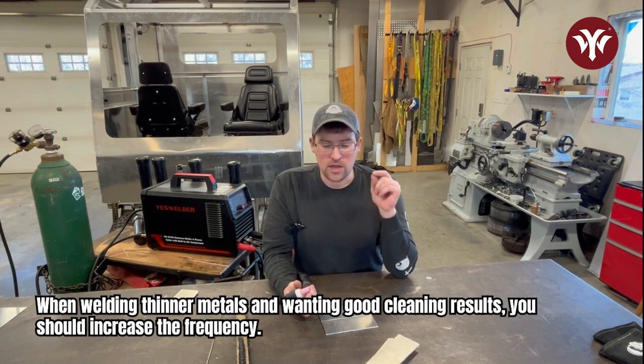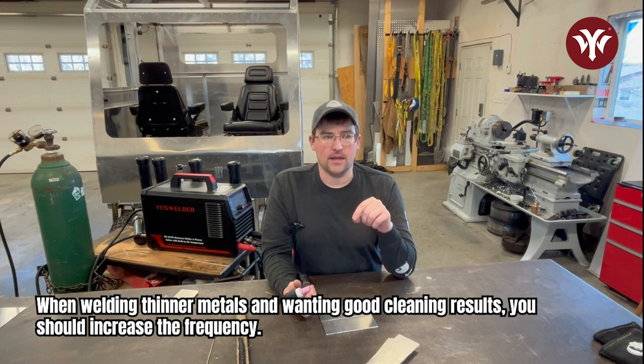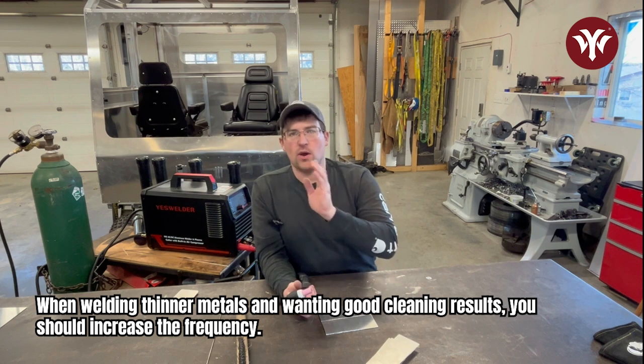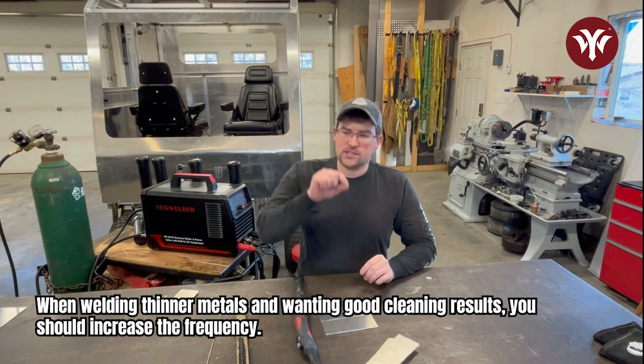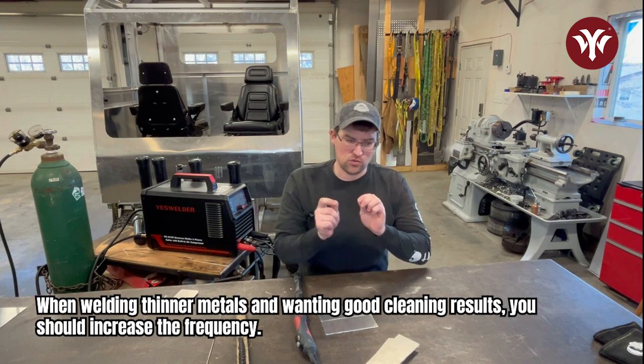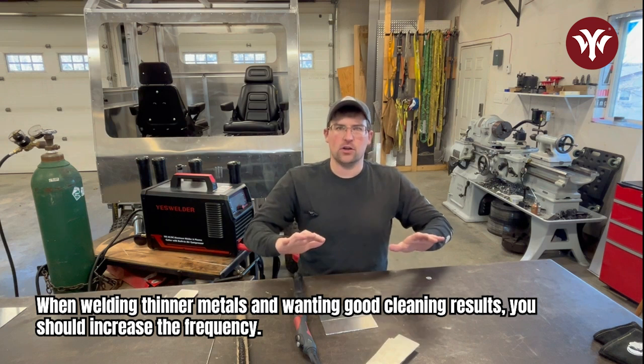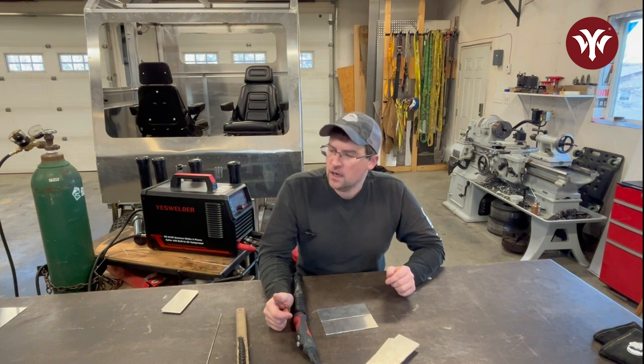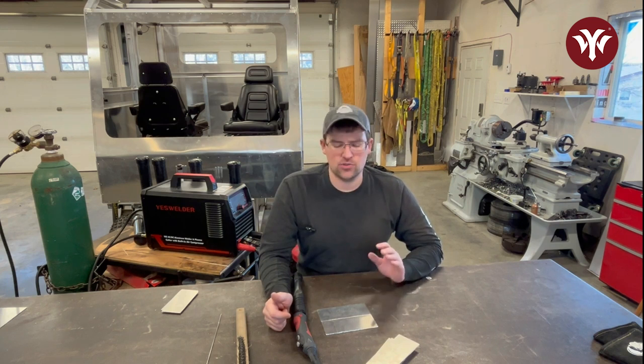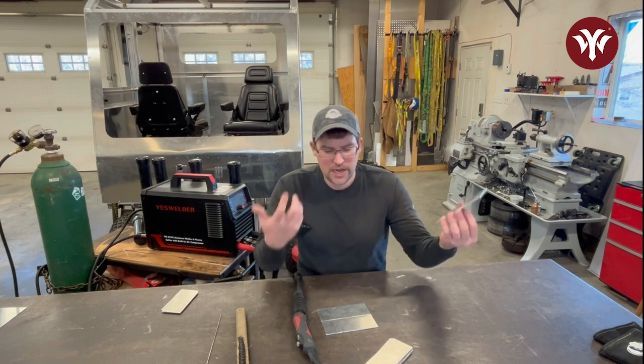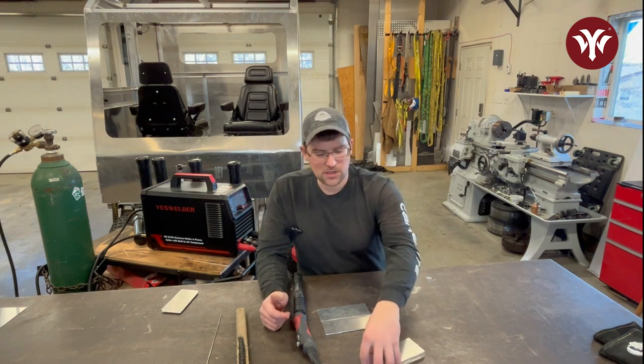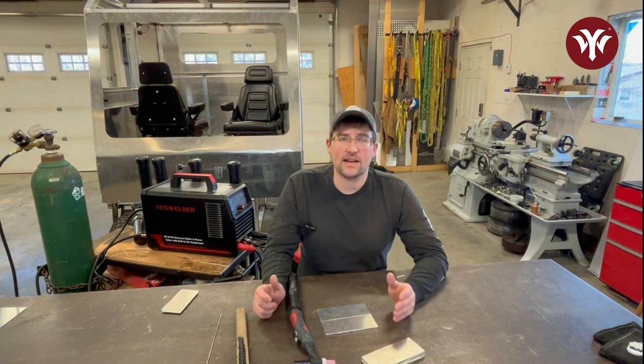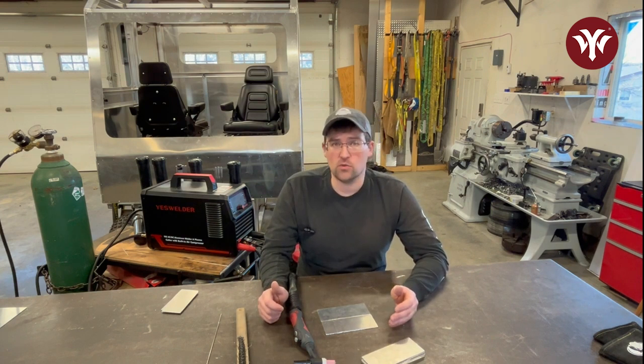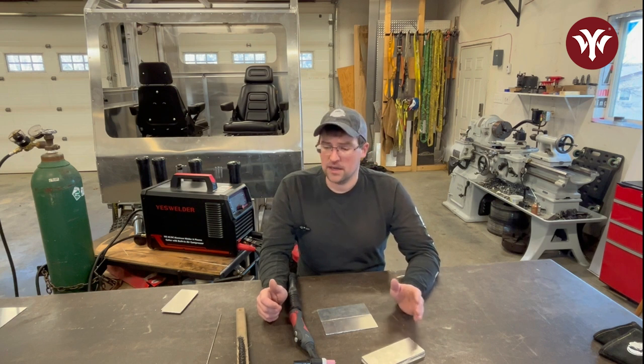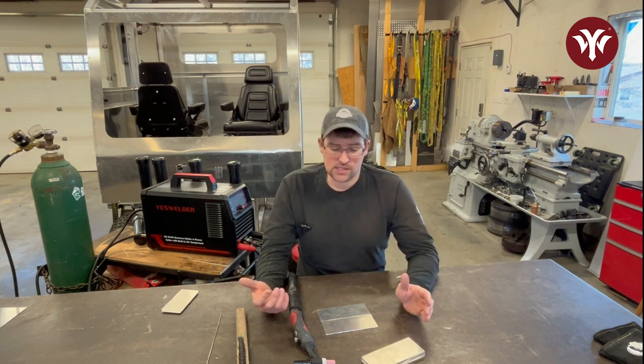If you need to weld thinner metal and you want to get a good amount of cleaning action, you're probably going to want to go up to a higher frequency because every cycle happens that much faster, which means you can move along a little quicker before you saturate your part with heat. I often don't play around with frequency too much. I typically weld kind of the same things. So it's something you can go ahead and play with yourself, but that adjustment is there. And if you want to learn more about it, go ahead and research a little bit on your own, but 85 to 100 hertz is where we're going to set this.